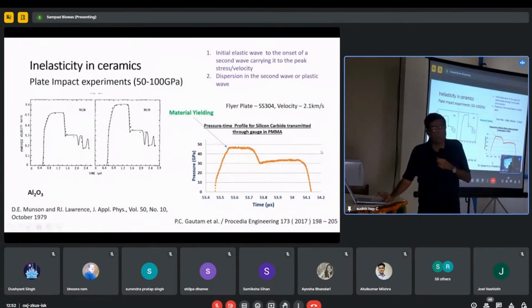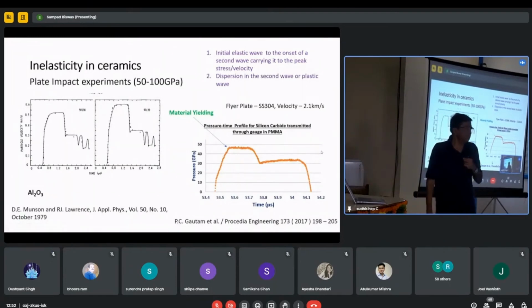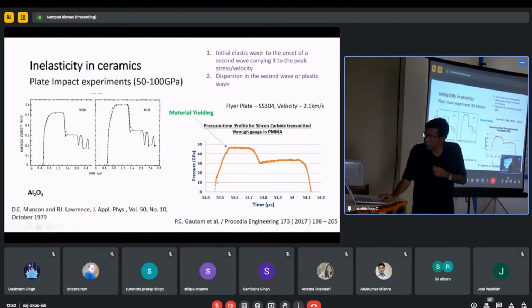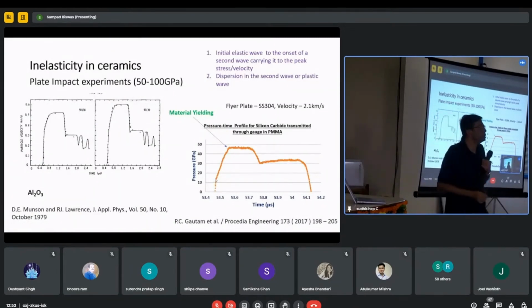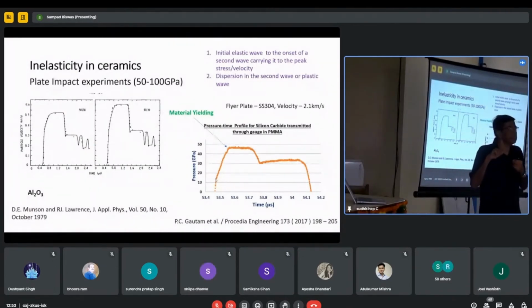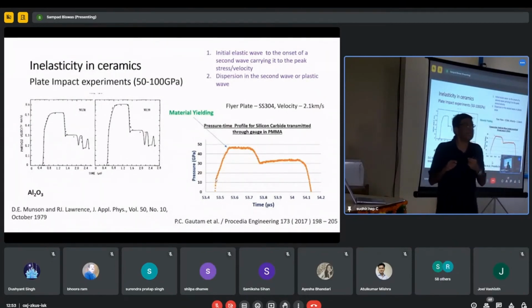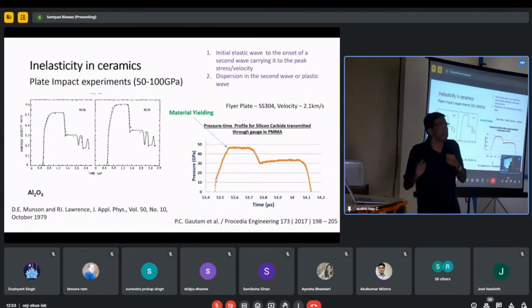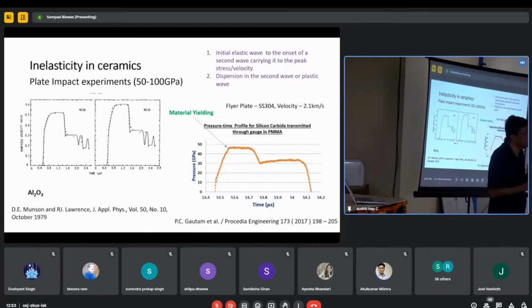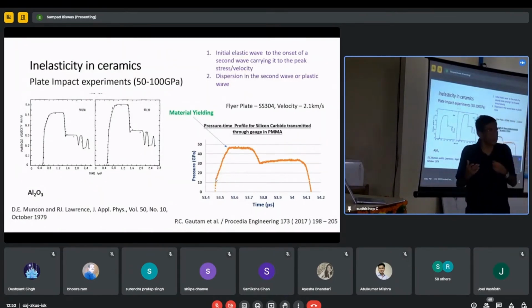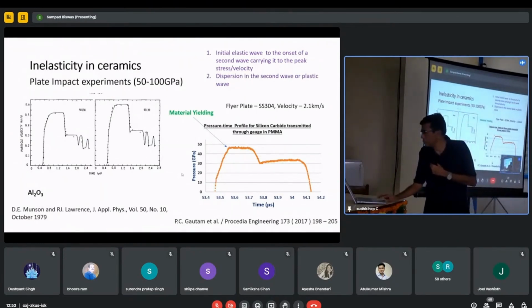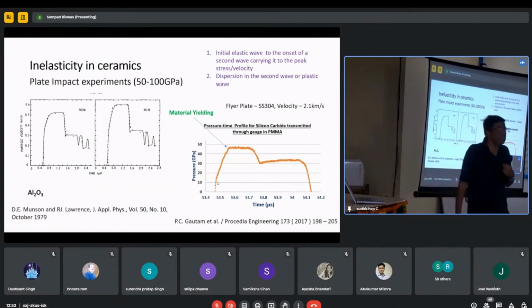Here is one sample's data I am showing now. You see, the inelasticity comes from this level. When it starts deviating from the linear elastic mode, this point is called the elastic limit, named after the scientist who discovered it, the Hugoniot elastic limit, or HEL. The Hugoniot elastic limit is a very effective parameter by which we can judge one ceramic against another. Now, the Hugoniot elastic limit here is very high, about 13 GPa, which we have found in the case of silicon carbide.